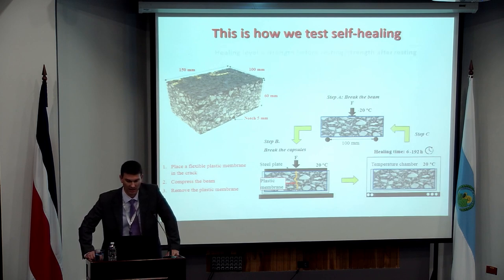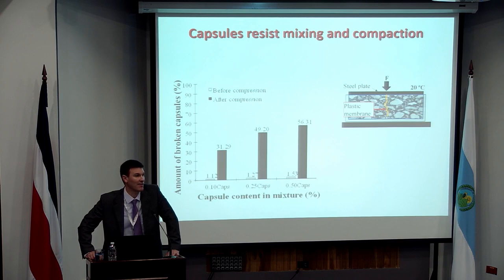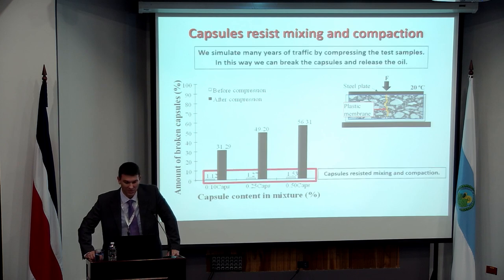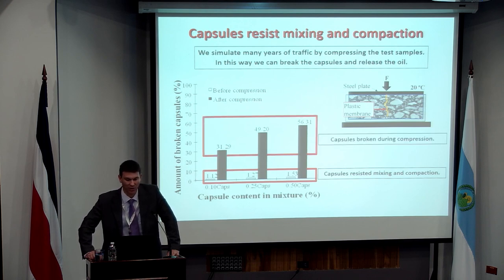So what do the results look like? The results actually were very, very encouraging. We do see some fracturing or some reduction in the number of capsules during the production process, but that's usually only about 1.5%, very, very small amounts. And then we see massive increases in terms of healing strength, in terms of self-healing of the material once those capsules break, where we can get anywhere up to about 50% of them breaking, depending on, firstly, the dosage. So these were done with three different dosage rates, and also in terms of the type of loading or the type of damage that we're experiencing in our material.